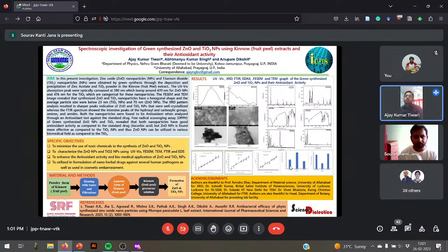The aim of my work is to synthesize the zinc oxide nanoparticle and titanium dioxide nanoparticle via a green route through the deposition and precipitation method of zinc acetate and titanium dioxide powder in the Kinnow fruit peel extract. UV-vis absorption peaks were observed at 380 nanometer, with a bump around 470 nanometer due to impurity, for zinc oxide nanoparticle and 476 nanometer for the titanium dioxide nanoparticle, which are categorical for the formation of the nanoparticle.